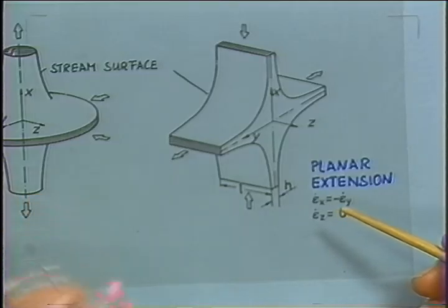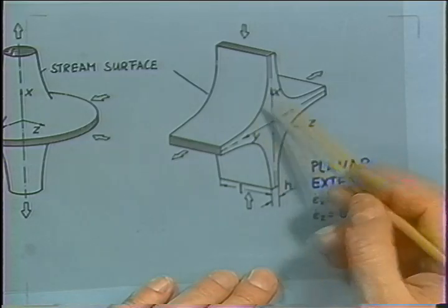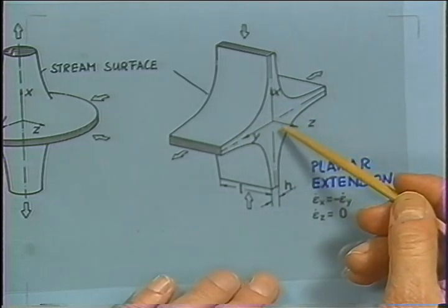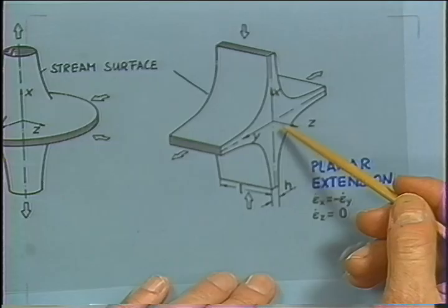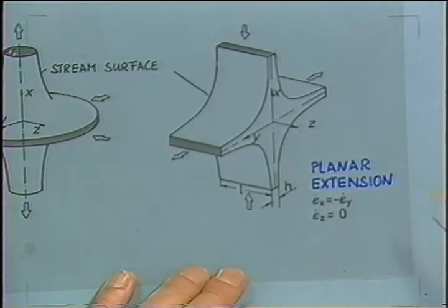It's still being stretched. So zero motion doesn't mean zero deformation. The motion is zero, but it's being stretched over a long time. And in fact, we can put windows on this side and on the back side, and then observe changes in the material by some optical techniques. And that's very popular. Keller, for instance, in Bristol looked at coil-stretch transitions in polymer solutions by exactly this technique. Or we built a die like this.